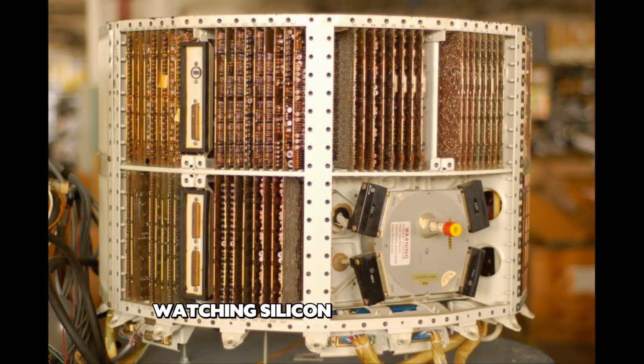Hoerni had been watching silicon wafers oxidize naturally in air after high-temperature processing. Silicon dioxide, essentially glass, would form a thin layer on the surface, and this oxide layer was remarkably stable. It didn't conduct electricity, it resisted chemical attack, and it adhered to the silicon beneath it with almost molecular perfection. In February 1959, Hoerni realized the oxide layer wasn't contamination to be removed. It was protection to be exploited.